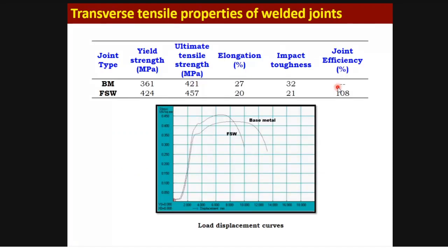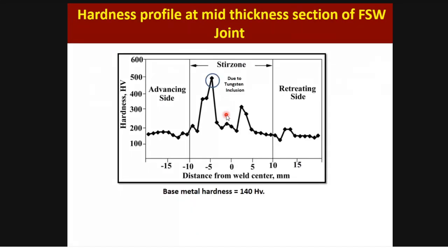But here we didn't compare with other processes, we just compared the weld with the base material. The base material strength is 421 megapascal. FSW has given higher strength than the base material, but elongation is less, 20%, and toughness also less. Okay, so only the strength is higher, but the ductility is reduced. Toughness is also reduced. So it was very interesting, and it's critical to us. Then we didn't know what the reason was, so we measured the hardness. The hardness at the stir zone is higher than the unaffected base metal and other areas.